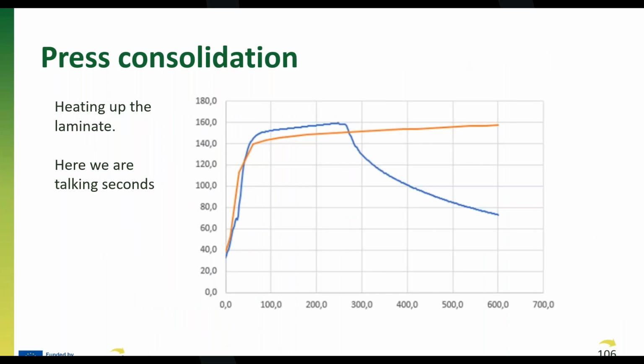As you see here, we have a very fast heating of the laminates because it comes in at room temperature, and after like 40 seconds, it's at the temperature you have put on. So that is going fast, not like minutes or hours like in the vacuum consolidation process, but here you are on a very fast process. Next one, please.